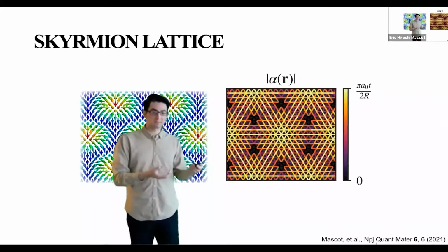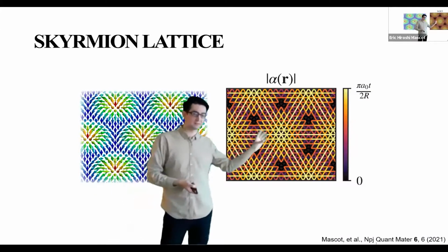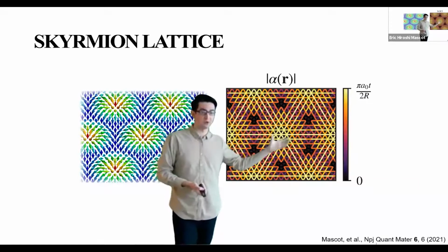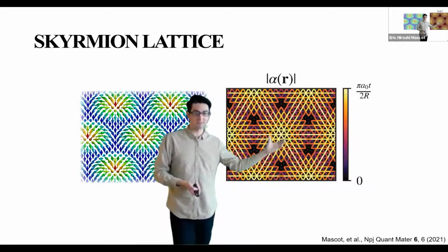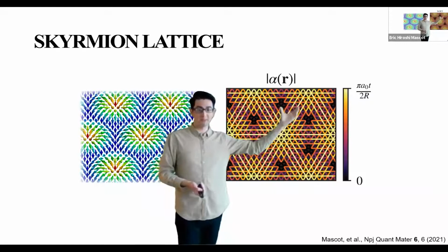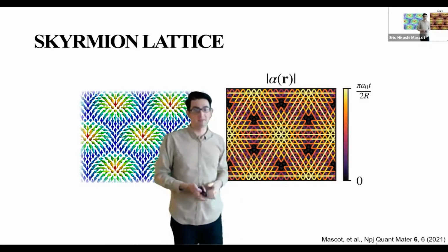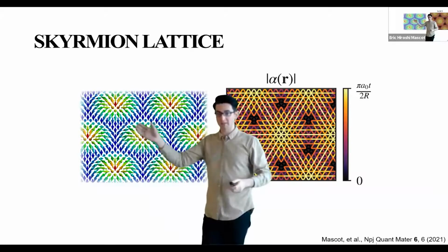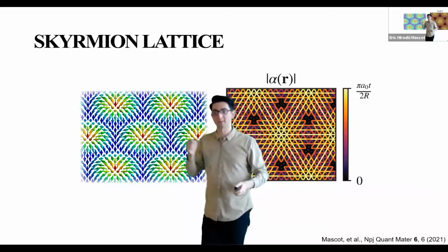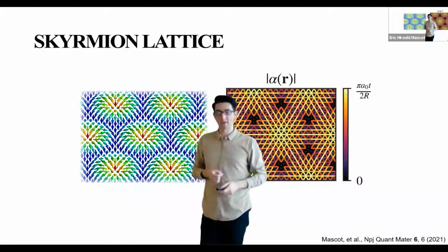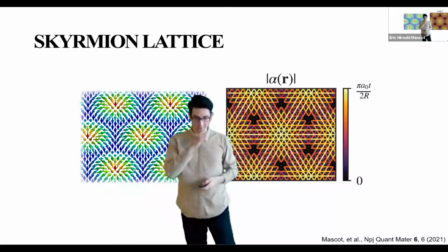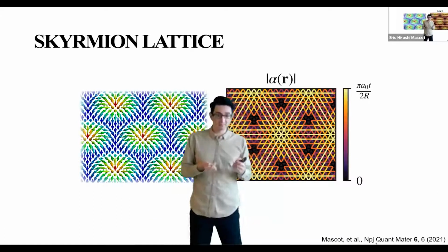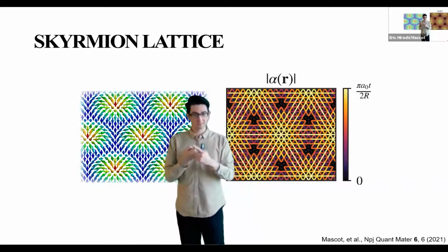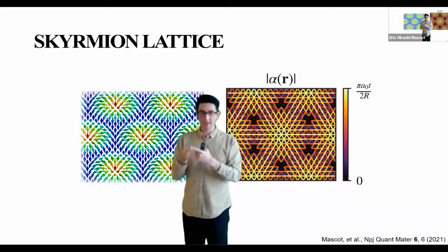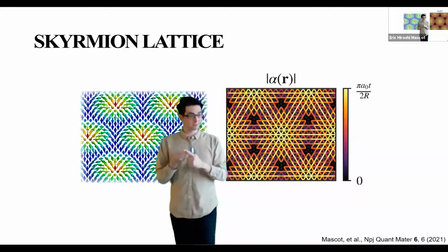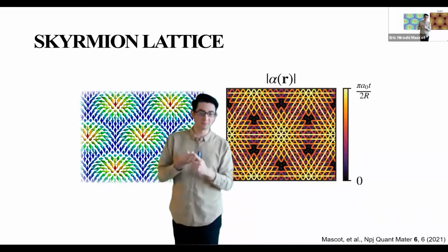And what we get is, at the center of the skyrmions, a very strong induced Rashba effect. But in the corners in between the skyrmions, a very weak effect, which you can see here locally, it looks ferromagnetic. And so we don't have an induced Rashba effect there. But with this, we have superconductivity, we have a Rashba effect, and we have magnetic ordering. So we have the 3 ingredients that we need for topological superconductivity.